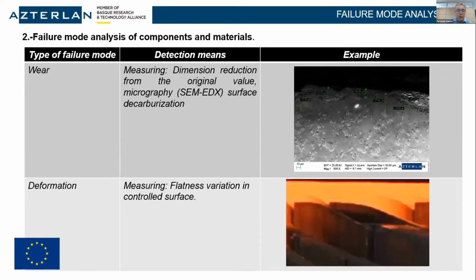Okay. What's wear? We can have problems with wear. Well, we will detect a dimension reduction from the original value, and we will show a surface that in our case is decarburized, has lost the presence of carbides, and it's more prone to wear. And of course, the deformation, we can observe in the right image that we have a flatness variation in this control surface. So these are some examples of how to define the failure modes in a correct way, so that we can define robust corrective actions.